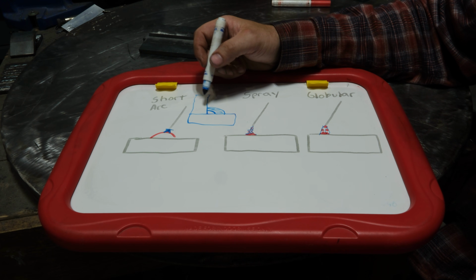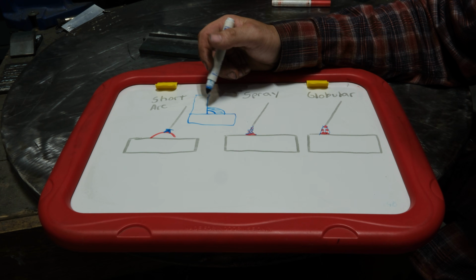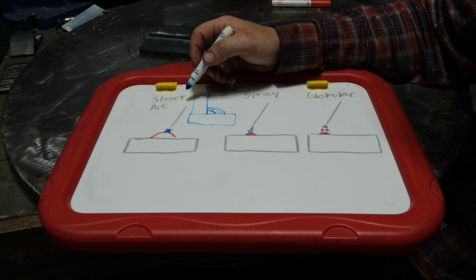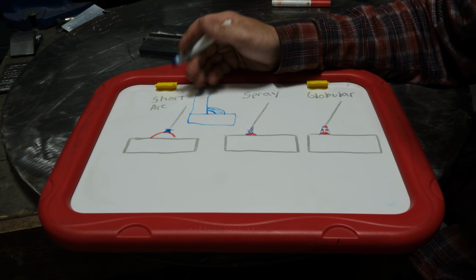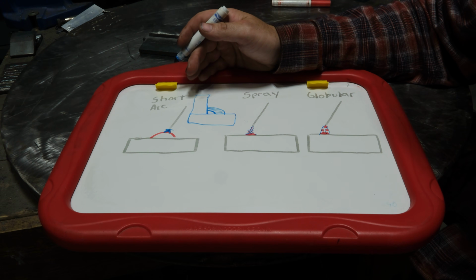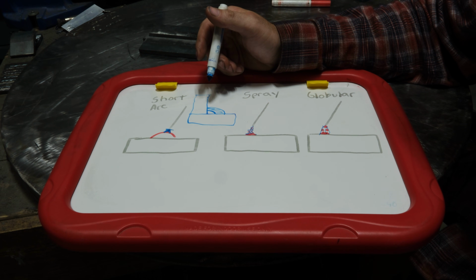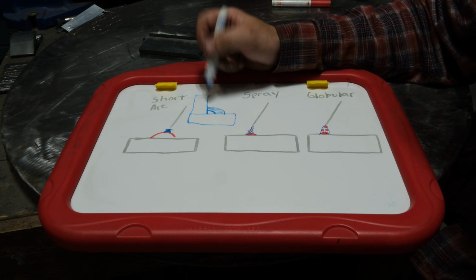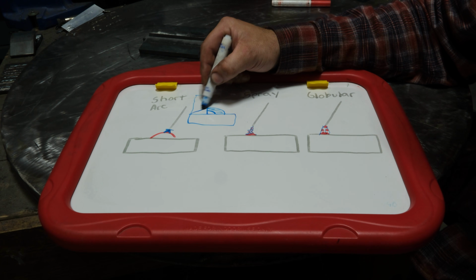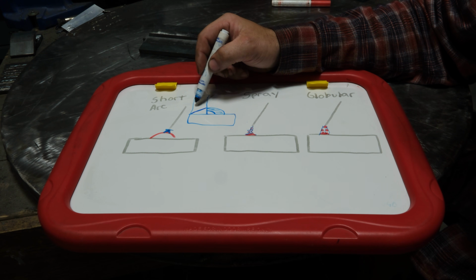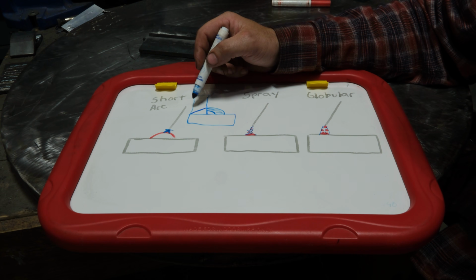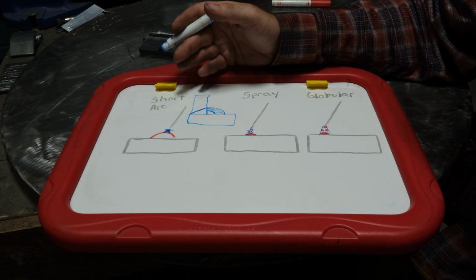I've done videos, links in the description, dealing with preheating and how that doesn't affect short arc MIG's ability to penetrate anything. It just makes the weld look hotter and flatter, but it still doesn't penetrate. And I've also done a video on beveling and how in many joint styles, in many cases, that simply is ineffective, because if it won't fuse anything on thicker plate, beveling it down to a knife edge on one member, like say on this, if you were to bevel this to a knife edge, you're still not going to fuse into the thicker material. You might get better fusion here, but that's it. So even that isn't a solution.